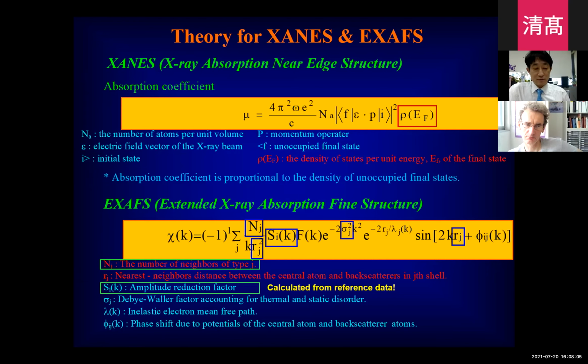For EXAFS, I think all of you are very familiar with this equation from the fitting analysis. Based on this equation, we can get information about the coordination number, the bond distance, and the Debye-Waller factor, reflecting the degree of disorder. I want to emphasize that the amplitude of EXAFS is not simply proportional to the coordination number. It's also proportional to the amplitude reduction factor.